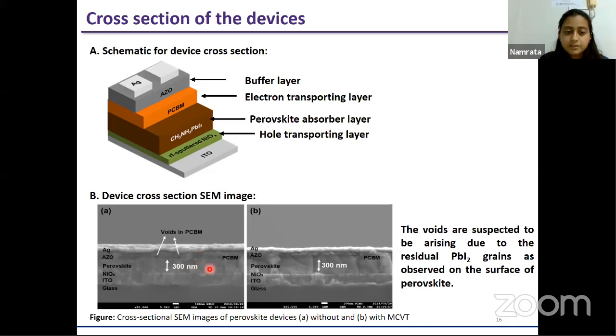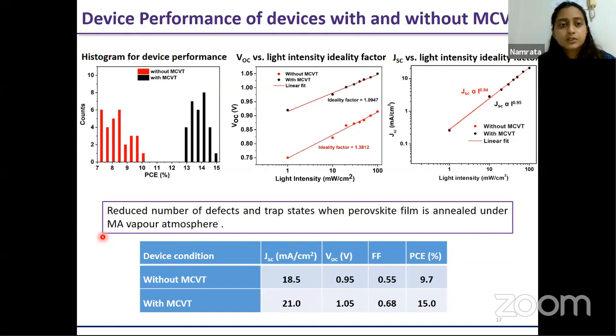So this explains why we have a lower performance when we are using the perovskite which is annealed as such, and why there is an enhancement in the efficiency. Of course, when the interfaces are smooth, the transport of electrons and holes towards the respective electrodes is smoother. And that is what we want in our device. The better the transport, the better the efficiency. So we made a batch of around 30 devices, and we observed that for all these devices, whenever we have a methyl ammonium halide vapor atmosphere, the devices perform better.